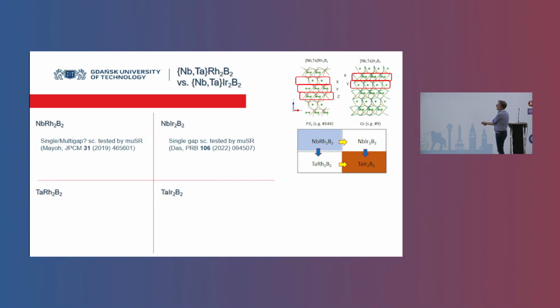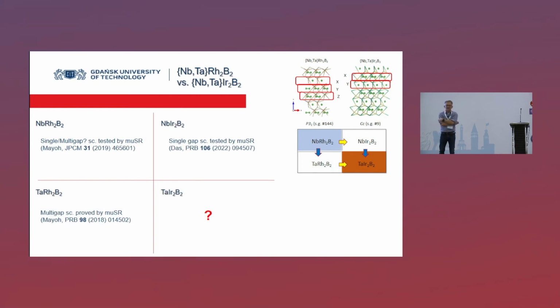A few weeks ago, Bhattacharyya Das published a paper showing that in niobium iridium 2 B2 there is single gap superconductivity. Tantalum rhodium 2 B2 was tested again by the Warwick group, and they found multi-gap superconductivity proved by muon spectroscopy, and we don't know about this one. We are waiting. Maybe soon we will be able to tell you about tantalum iridium 2 B2. But when you take a look at this picture, you realize that that one is actually the heaviest one, right? Because you go from niobium to tantalum, and from rhodium to iridium. So all the elements that are important for the superconductivity are there. And we hope that one will also be a multi-gap superconductor.